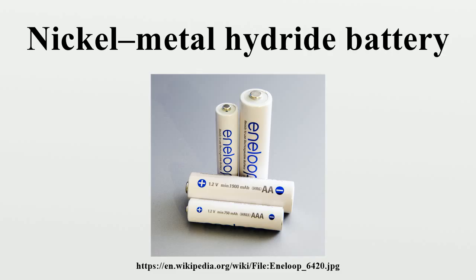By using an improved electrode separator and improved positive electrode, manufacturers claim the cells retained 70% to 85% of their capacity when stored 1 year at 20 degrees Celsius, compared to about half for normal NiMH batteries. They are otherwise similar to other NiMH batteries, and can be charged in the typical chargers. These cells are marketed as hybrid, ready-to-use, or pre-charged rechargeables.